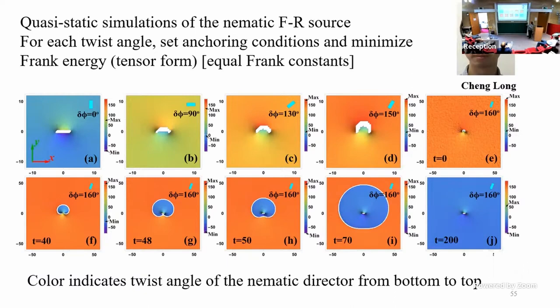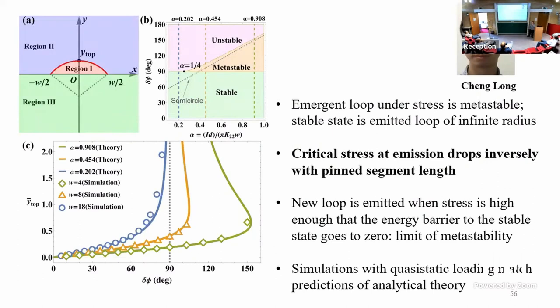Okay, so Cheng and Jonathan also developed an analytical calculation, just like you can do for a regular Frank-Read source in a crystalline solid. There's a higher energy density outside the loop. There's a lower energy density inside the loop because it's untwisted a little bit. Plus there's an energy cost associated with the line tension. And they demonstrated that the analytical model really matches the quasi-static simulations.